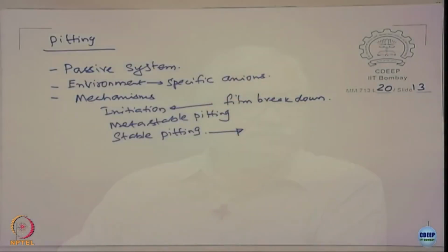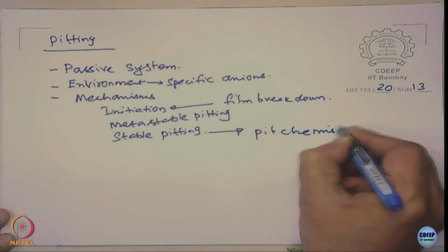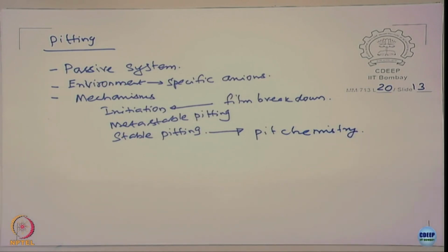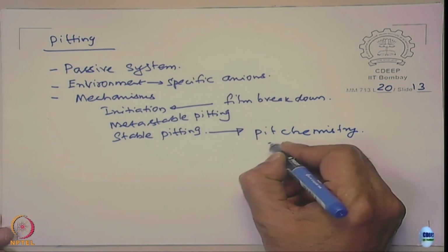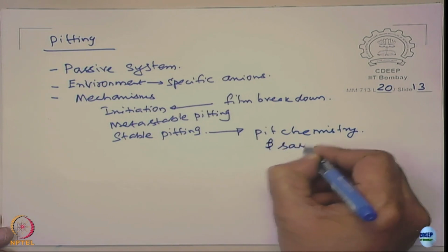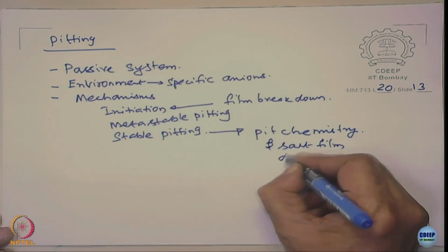And the criteria of a metastable pitting turning into a stable pitting, right. What is the criteria for this? When does it become stable? Yeah. When does it become a stable pit? Pit chemistry. Yeah, it's a pit chemistry, right? The pit chemistry is special. It has more H plus, it has more chloride, so it does not allow the metal to repassivate. So that is governed by what? Salt film, diffusion effects.